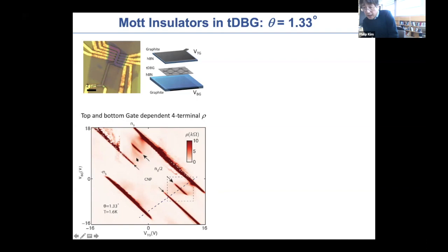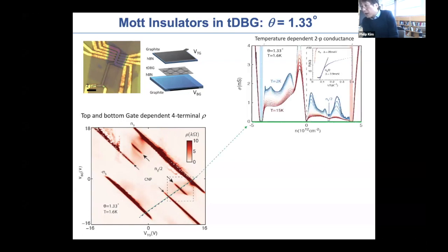But interestingly enough, between the neutrality and the full filling, once you get to half filling, this dark color means that large resistivity appears, and that only appears at finite displacement field, which flows in that direction, right? So the appearance of this high resistance state indicates indeed that there is an insulating state that we can stabilize by this displacement field in the half filling range. One can do a little bit more careful work. For example, you can measure the size of the gap, and the gap in this particular case, about 1.33 degrees, is something like a few millielectron volts.